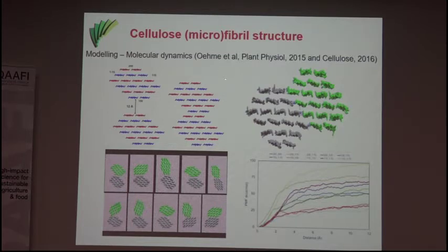So that was the other work that Daniel published. So the 18 chains in plant CESA, and then in cellulose we published how these things interact, doing molecular dynamics on bringing them together in various orientations. You can see there's just two various orientations, and interestingly sometimes you get water traps, sometimes you don't. And that depends on the orientations that you allow.